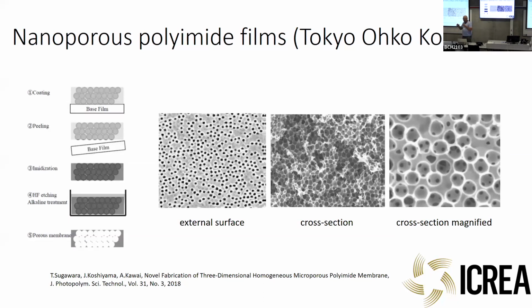I don't know how they do this, but they achieve very homogeneous structure with very high volume fraction of nanoparticles, and then they polymerize and they etch out the silica. And they obtain this kind of structure with funny pore structure, like nano cavities connected with bottlenecks, something like that. But these bottlenecks may be like 20 nanometers, the cavities are like 100.